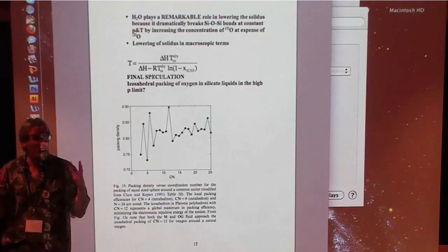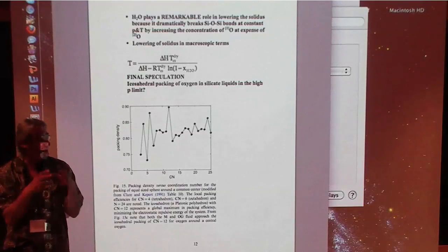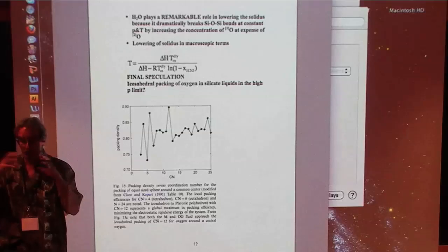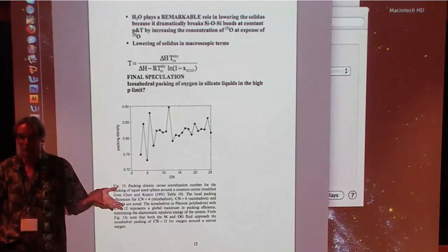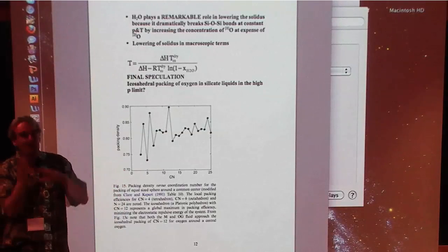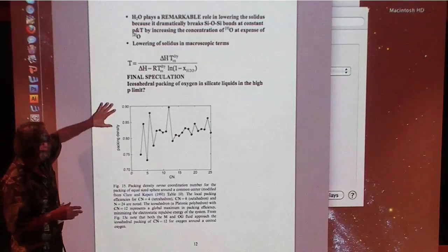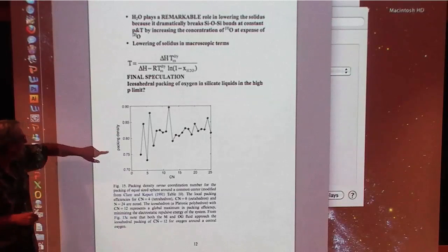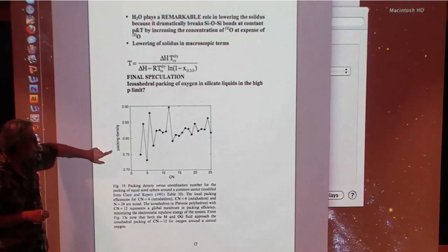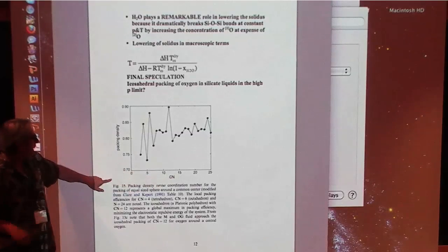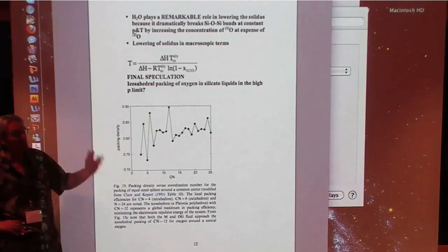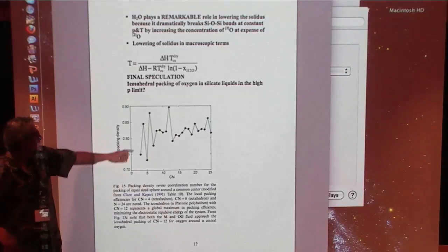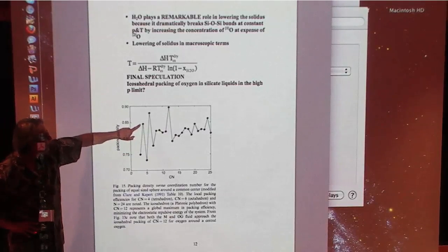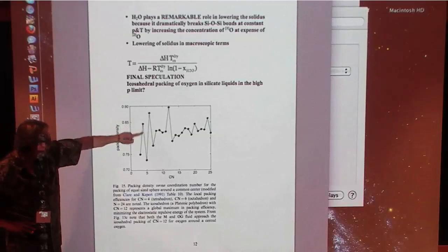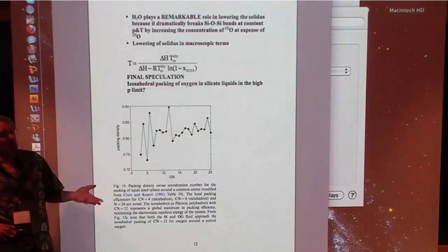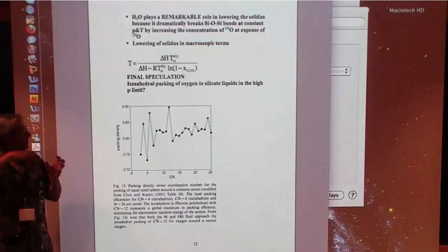They're basically packed oxygen spheres, repulsive spheres. That's really what a silicate is. 90% by volume oxygen. Forget about all the other stuff. What this plot shows is packing density as a function of coordination number, and it shows the things we all know. Why are silicates based on tetrahedral packing? Because that's a local maximum in packing efficiency. This is 4, tetrahedral. Why do we have stishovite, with silicon in 6 coordination with oxygen?